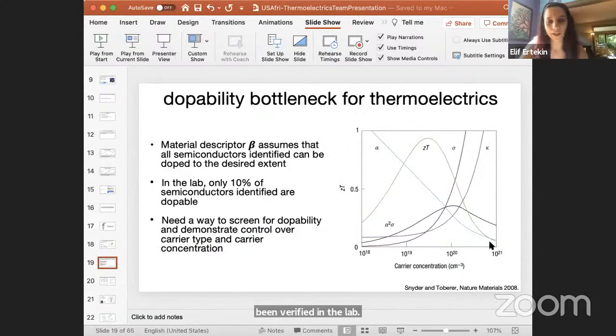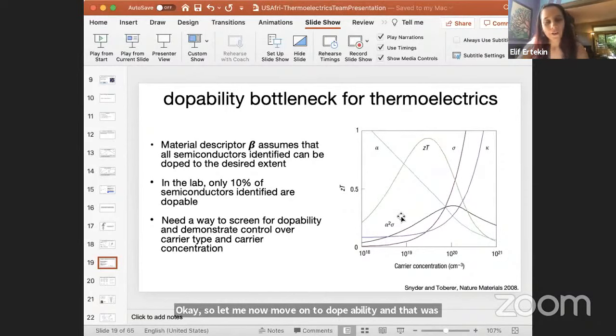Okay, so let me now move on to dopability, and that was the second point of our funnel. Although this quality factor beta proved to be an effective descriptor of a semiconductor's thermoelectric potential, a new bottleneck quickly emerged in our work, and that was related to the dopability of the semiconductor. The reason is that this quality factor beta neglects semiconductor dopability. It assumes that the semiconductors identified can all be doped to the desired carrier type and concentration.